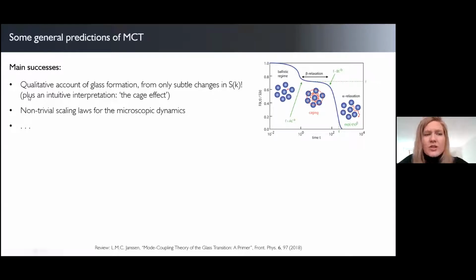And as a bonus, it also gives an intuitive interpretation of that phenomenon in the so-called cage effect. So that follows essentially from the theory, if you look closely at the equations. And so the cage effect is essentially saying that you get a slowdown of the dynamics because particles become trapped in local cages formed by the neighboring particles, which induces a strongly nonlinear feedback mechanism that slows down the dynamics enormously.